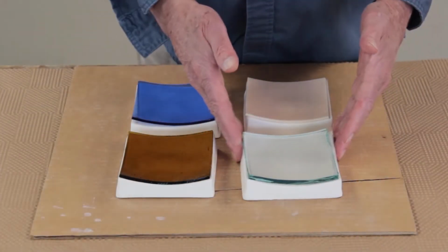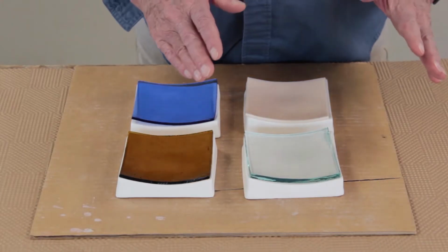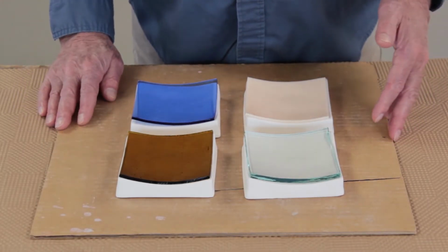As part of the experiments, I did some firings with the art glass firing onto ceramic tiles, and I was quite surprised to find that when I fired it to low temperatures, it didn't stick at all. And I did some tests to confirm it, firing onto small slumping molds. These are molds that had never been kiln washed. They were brand new molds, never been used for anything.